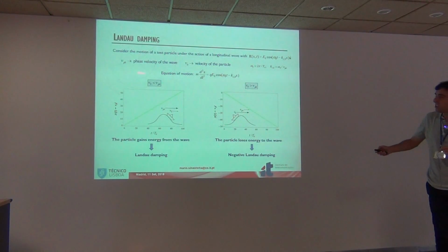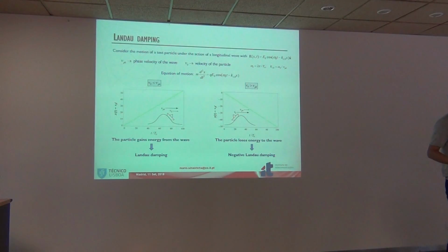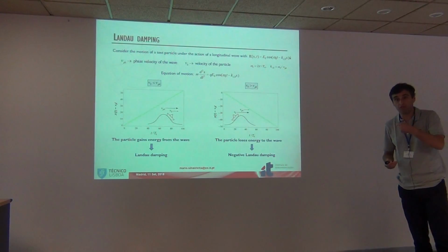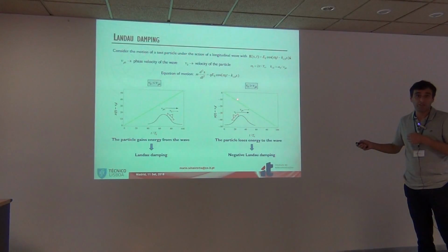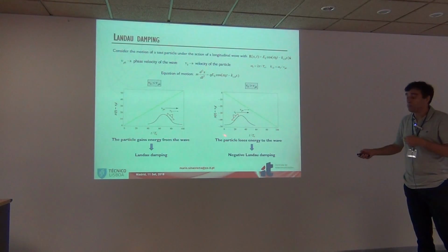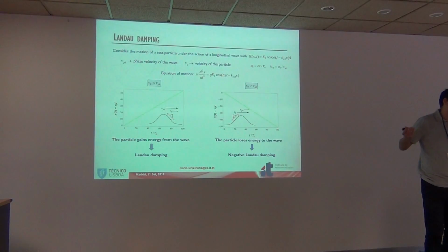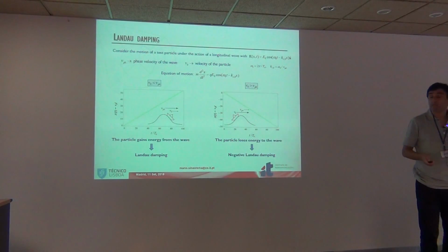In usual materials, this is not the mechanism that dominates, because most electrons will feel the other situation, so you have Landau damping. But if you inject the current in your graphene, you can put many electrons with velocities larger than the phase velocity, and then you can have this mechanism dominate, or in some conditions at least. And so you can have this gain.